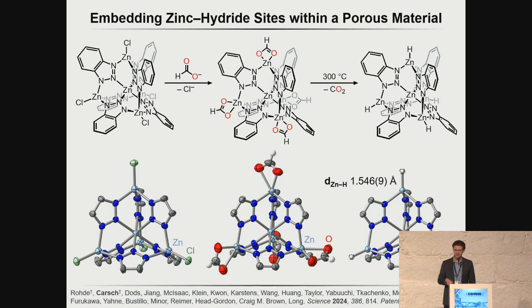We can resolve the hydride in the difference map using single crystal X-ray diffraction, but we can also use neutron diffraction and also validate the presence of a hydride using a difference map with infrared spectroscopy. So we can decorate this material with a very high loading of metal hydride sites that could potentially be used for carbon dioxide binding.